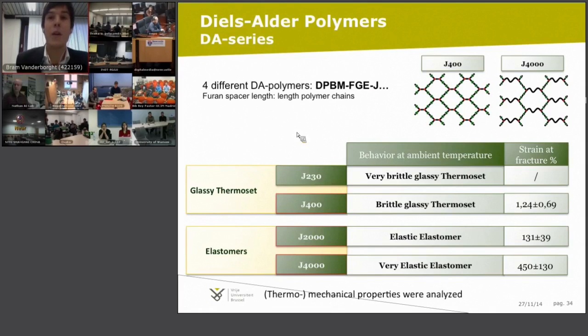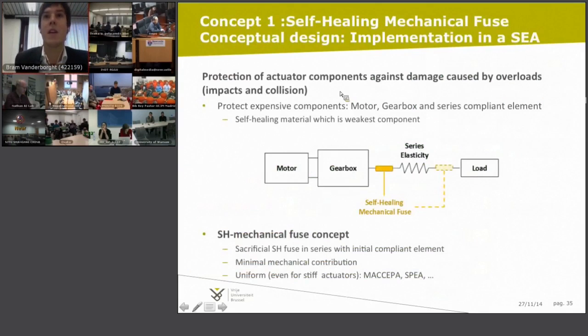So we will use different materials depending on the application. We will use the same material, but in different series, to obtain different applications. We developed two concepts. The first one is a mechanical fuse. The idea is that if you have an overload, we make the fuse the weakest element, so that it will break instead of the gearbox or the compliant element, and then we can self-heal the fuse again automatically.